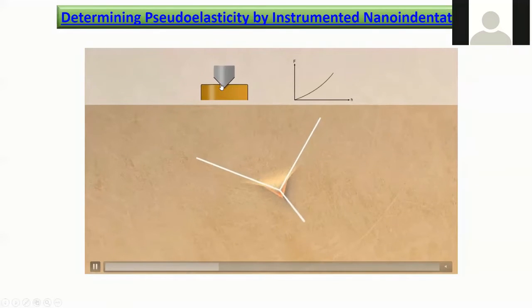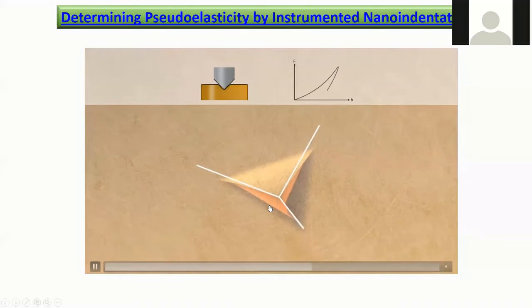So we basically indent with a sharp tip and we create an impression. We get the load versus depth of penetration curve. And from there, we can understand the hardness of the material, the elastic modulus of the material, as well as how much depth it can recover, how much depth is permanent, and so on.